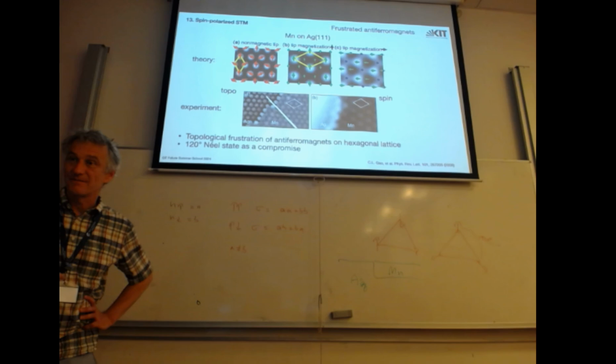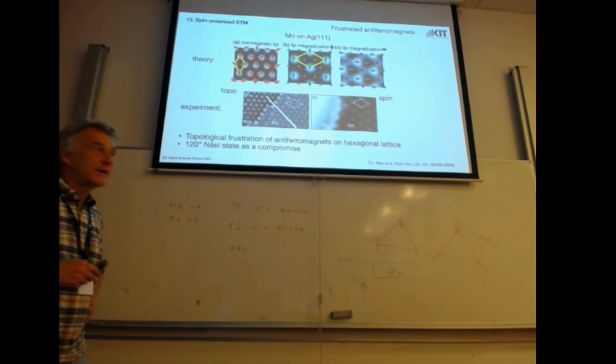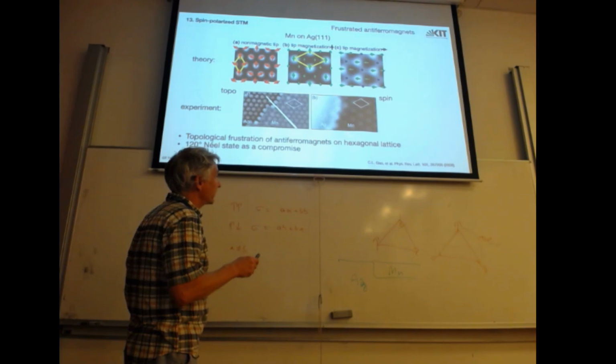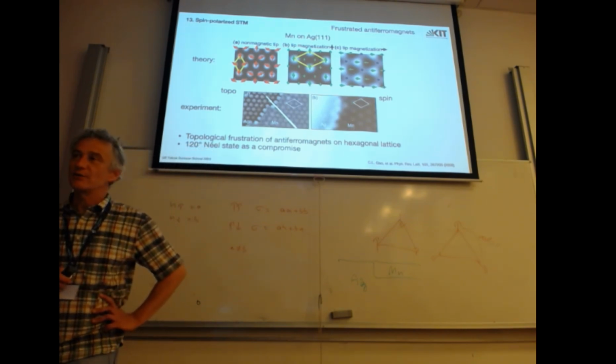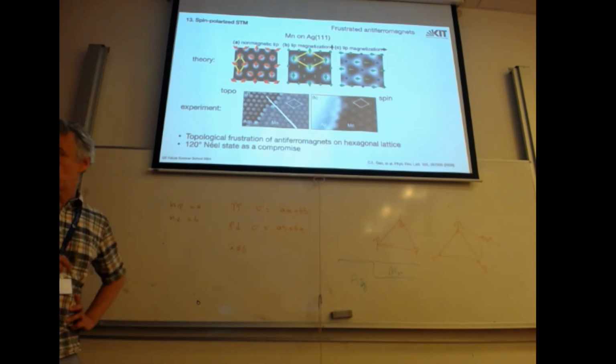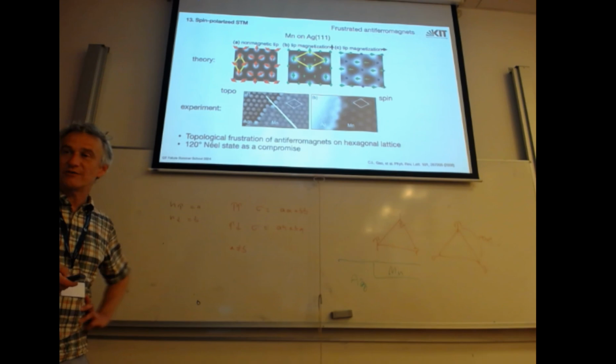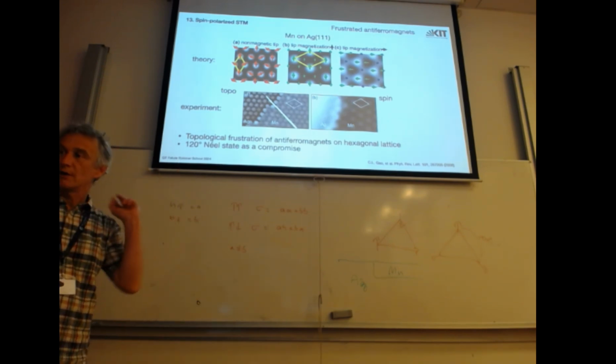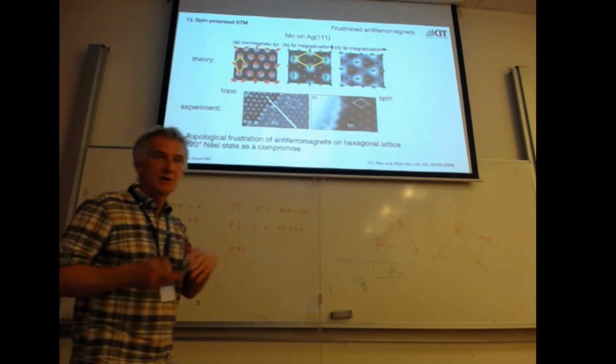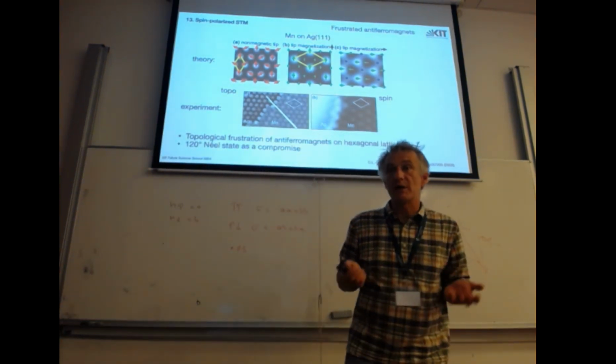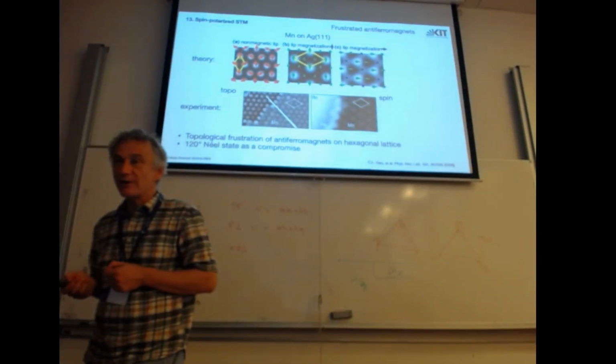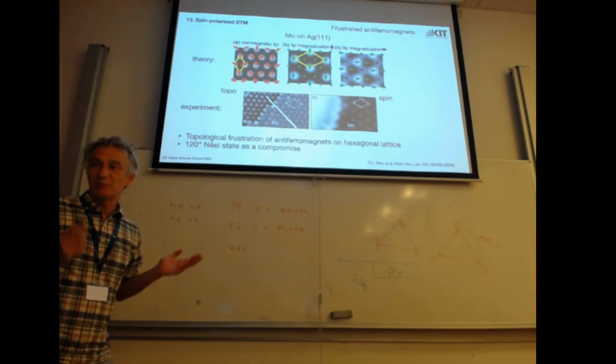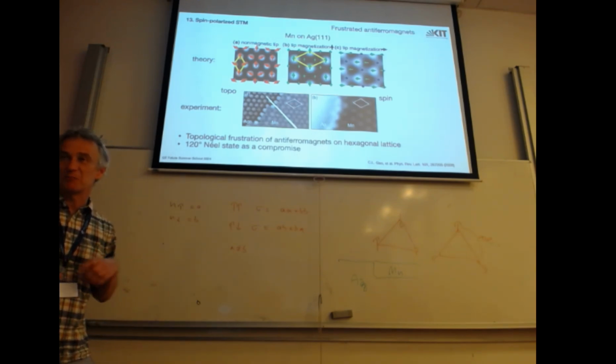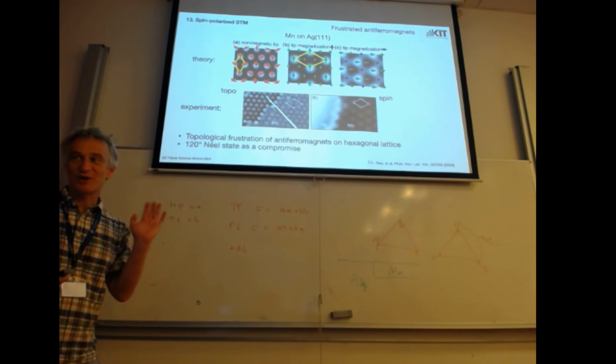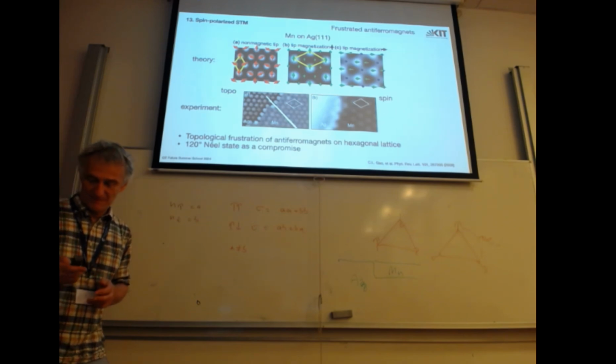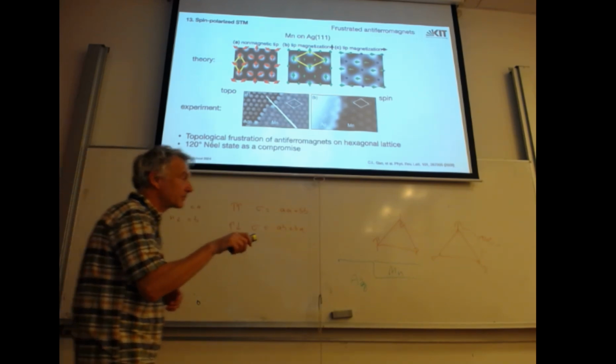Is there a way to change tip magnetic polarization? Yes. So this would be a simple thing. This is an antiferromagnet. It will not react to external magnetic fields, but the tip, you can choose a ferromagnet, and then you apply a magnetic field, and then your tip magnetization will follow your external magnetic field, but the antiferromagnet is unchanged. That's the simplest way, or you pulse the tip, you will change the tip configuration by chance. You have a last atom which now points into a different direction. Actually, I have examples where we exactly did that.